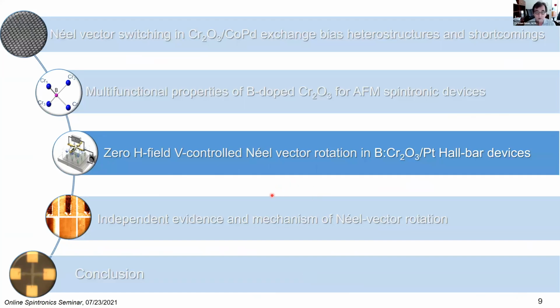Now I want to show you, if we can't do exchange bias systems, what else can we do? And it turns out we can create devices with reduced complexity, get rid of the ferromagnet on top. Don't worry about pinning. Just read out the boundary magnetization directly. And a way to do that has been established already in pure chromia with the help of Hall resistance measurements.